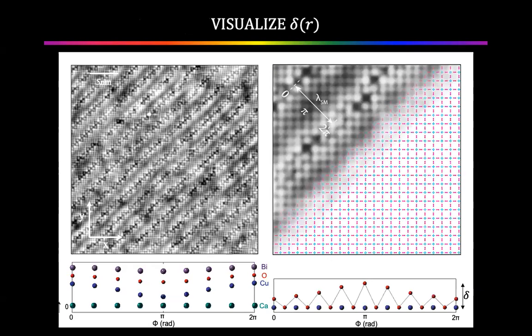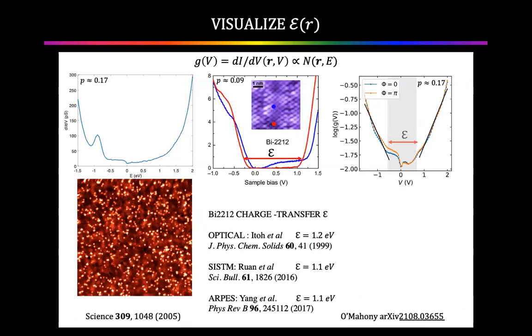All right. Now, in the STM, we have enough precision where we can see this is the line of maximum. That's the zero phase of this supermodulation, it's called. This is pi, halfway through the cycle. This is 2 pi. And in a field of view like this, we know where every copper is, we know where every oxygen is. We have enough geometrical information to tell us where every object is in this field at the atomic scale. So our working hypothesis is that by imaging the surface distortion, we can determine the apical distance as a function of location throughout the unit cells. So that's the first thing.